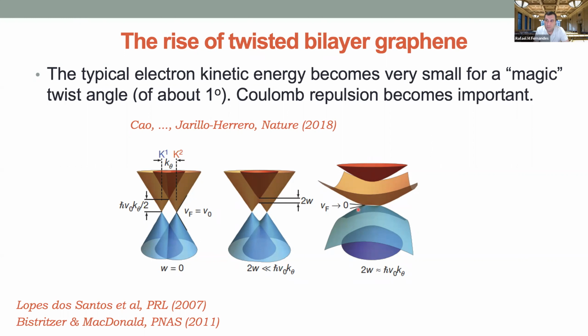Okay, so there was the so-called magic angle where this happens, which is about 1 degree. And if I have a nearly flat band, Coulomb repulsion becomes important, and I have strong correlation effects, which don't happen in just regular monolayer graphene.